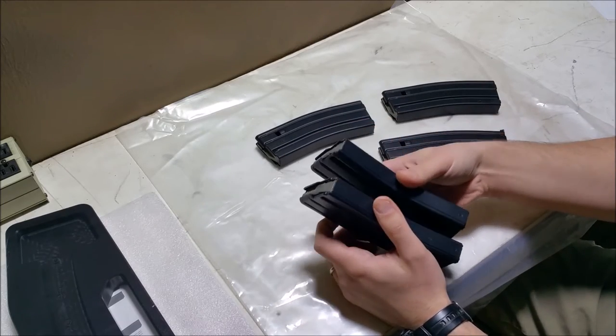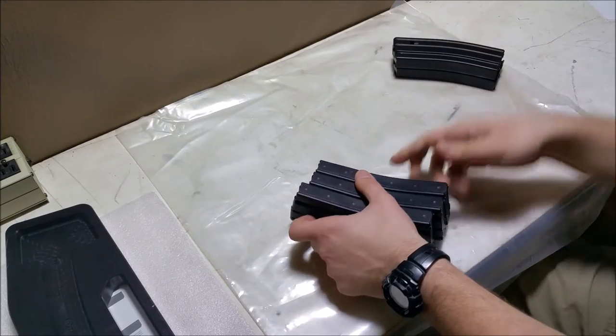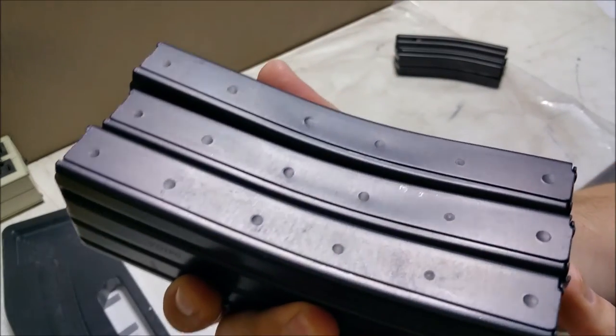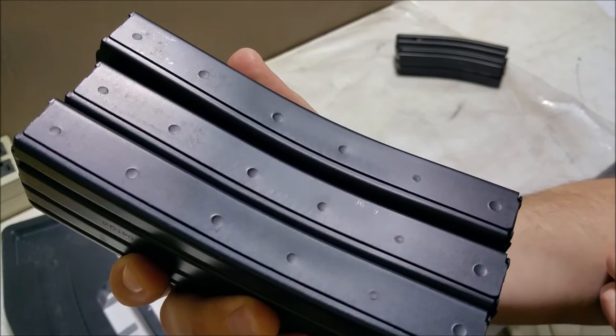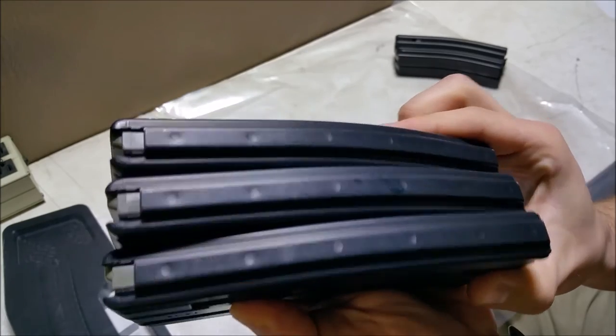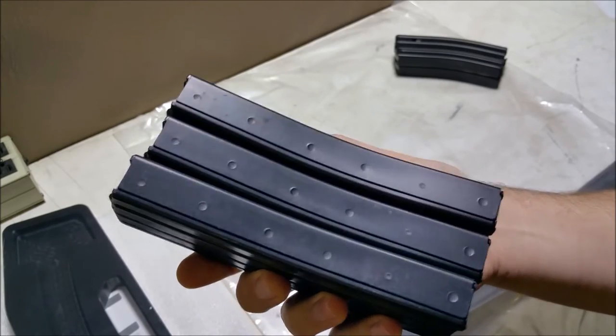Two out of the five are completely flawless and perfect. What I'm looking at right now are the resistance weld marks, the spot weld marks on these things. These two mags right here are fine. And these three here — the only thing I could find that looked different or off — if you can see the second from the bottom resistance weld, these look like they weren't quite completely welded. The spot weld marks are just a little bit smaller than the rest of them. It's just that one little weld mark right there that I think probably made them not completely pass QC over at D&H.